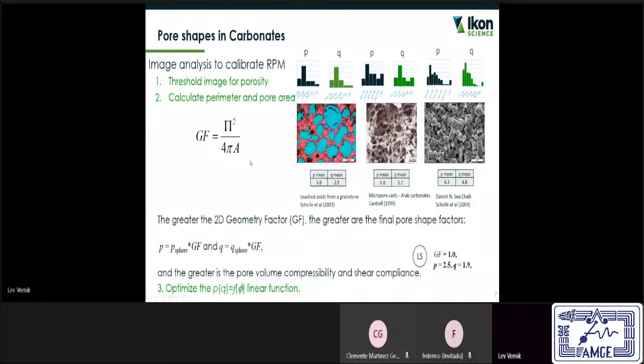A significant element that is missing in the sandstone environment is the complexity in pore shapes in carbonates. So when you're talking about carbonates, you can see all kinds of different pore geometries, and it's virtually impossible to prescribe any kind of simple geometrical shape to specific shapes that we observe lithographically or in scanning electron microscopy in carbonates. So one trick here is to use what Robert Zimmerman suggested, and he introduced a so-called geometry factor, which would be a function of the perimeter of any specific pore and its area. So if you know the perimeter and you know the area for each specific pore using image analysis, you can